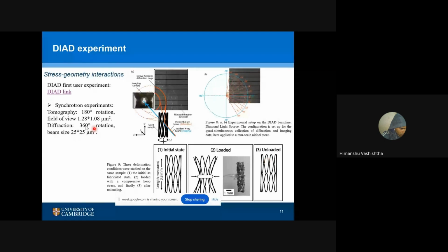To capture these things, we have taken the 180-degree rotation for the tomography. For this imaging, you can rotate your stage only, where your sample is. You cannot rotate either the detector or the X-ray beams, because the X-ray beams are at very high energy, so you cannot disturb them. So we rotated the stage by 180 degrees to capture the tomography, and for the diffraction, a 360-degree rotation was used.